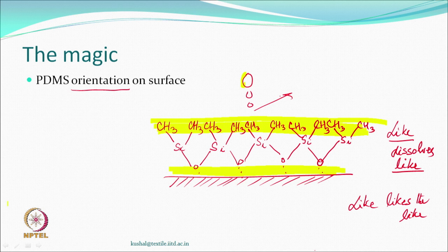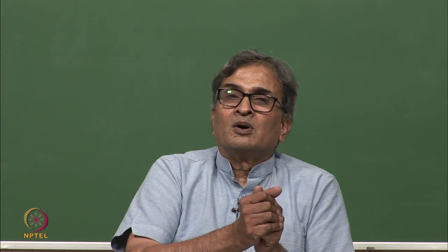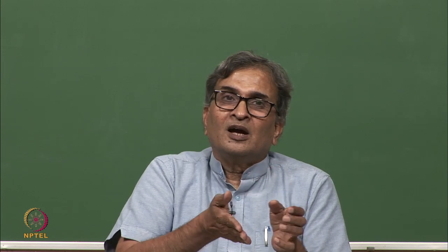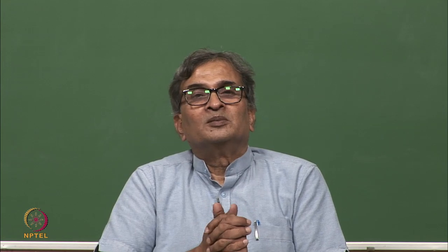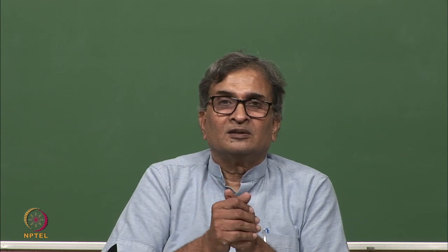Of course, you may have compounds in the market which may have the polydimethyl siloxane, and also along with it they may have polymethyl hydrogen siloxane, so that the hydrogen group will also become reactive. It can react with the oxygens of either the silicon based oxygens which are there, or the substrate oxygen, and it can become a more reactive film which would have reacted with itself, the molecules, or would have reacted with the substrate. So, that way wash fastness can also increase.